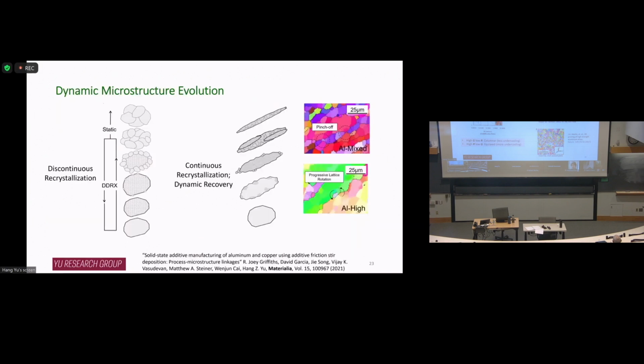In our case, we don't have to worry too much about that, right? Because this is a deformation process at high temperatures. We have dynamic recrystallization, right? And depending on your material properties, you may have 2 types: so-called discontinuous dynamic recrystallization versus continuous dynamic recrystallization. Discontinuous recrystallization is more like the traditional concept. You have a lot of dislocations, and there's a region with a dislocation-free grain, and that grain can grow to consume the neighboring grains to reduce the stored energy, right? And when this new clean grain becomes big enough, you get more dislocations inside. And you can repeat this process in a cyclic fashion. That's called dynamic recrystallization in a discontinuous way.